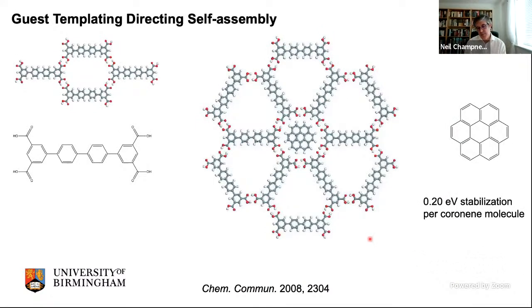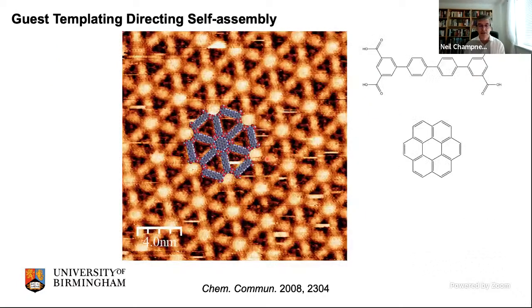We then thought, there was a paper back in the 80s in Helvetica Chimica Acta which said that coronene is the right size to fit within 6 isophthalic acid units like this. Okay, so we thought, can we add coronene? The answer is yes. Here's coronene added to the same solution, the same drop of nonanoic acid. The coronene adsorbs to the surface strongly because it's interacting with graphite, and you end up with 6 of these tetracarboxylic acid molecules surrounding each of the coronenes.